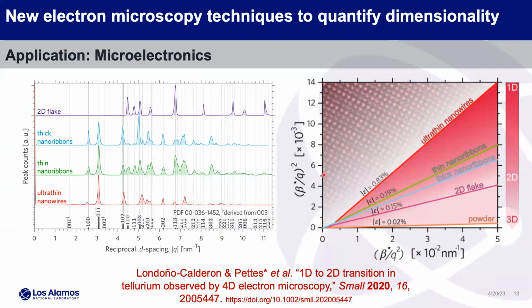So what we found, this is a Williamson-Hall plot. For those of you who do refinements, it's just plotting in a certain way: the full width half max of each of these peaks over the Q vector. We can plot these, and we saw a nice trend that we didn't expect we could see with this method, which is the microstrain. The intercept and the slope give you microstrain, and mainly in this we're looking at microstrain, but the microstrain is different in the 3 nanometer nanowires compared to the bulk, compared to the powder that we did X-ray diffraction on.